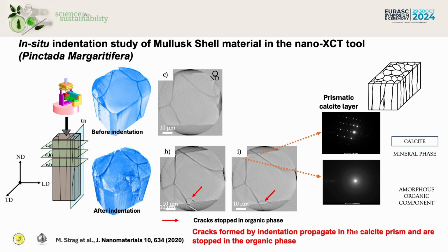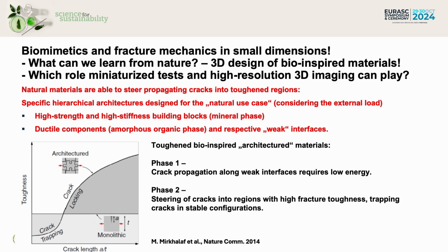Okay, here you see it on the left-hand side, and on top there is the microstructure of the mollusk shell before we did this indent. And then after the indent, in the lower image, you see the cracks. And the crack is going through the calcite, and we have shown this with the TEM images, the crystalline structure, and then we have an amorphous phase where the crack is stopped. And it seems that this is a very general principle of nature, that we have a two-step process.